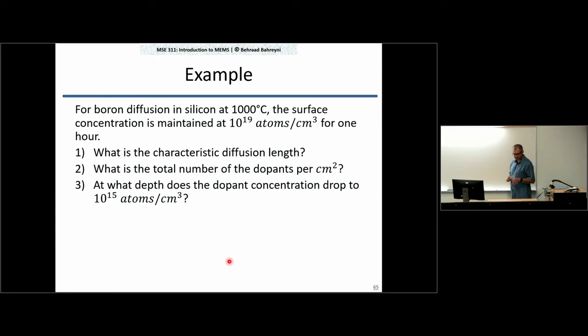So what is the characteristic diffusion length? What is the total number of dopants per centimeter squared, right? So that's the areal density. And then the last question is, at what depth does the concentration drop to 10 to the 15 atoms per cubic centimeter? Let's say that's the background concentration of my wafer, I want to know how deep I should go into this wafer before my doping goes back to the background concentration from the p-type that I'm doping it. Okay, so let's solve that.